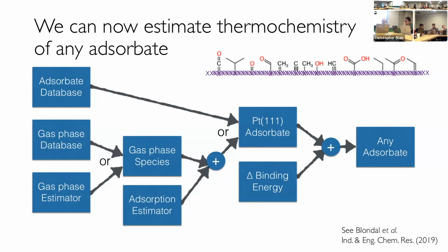It's assuming that you're taking the molecule and putting it at its lowest energy configuration on that surface. If you use a different facet, then there can be a different configuration for that atom, and that throws the assumption out the window. So it's better to use these with just a single metal facet. Don't mix and match, like the 211 and the 111 facet.